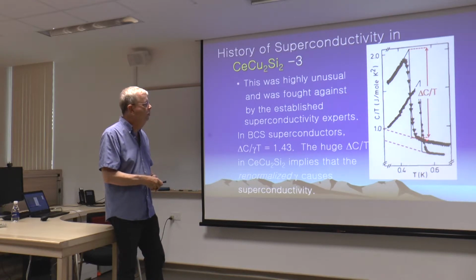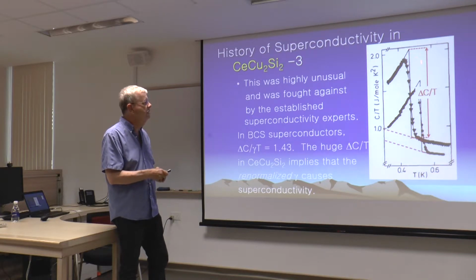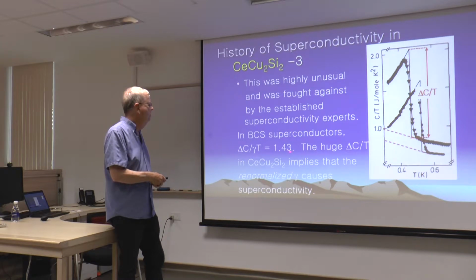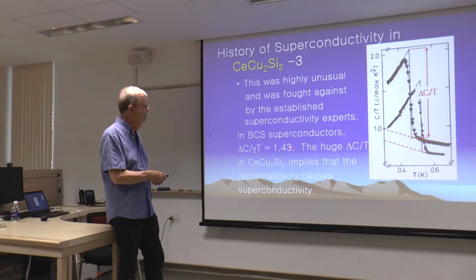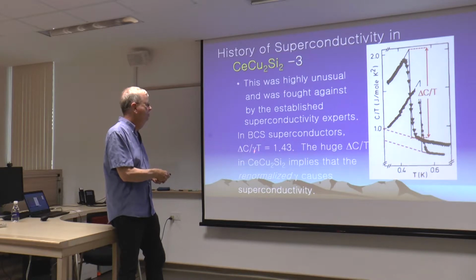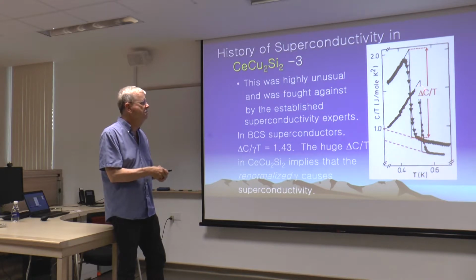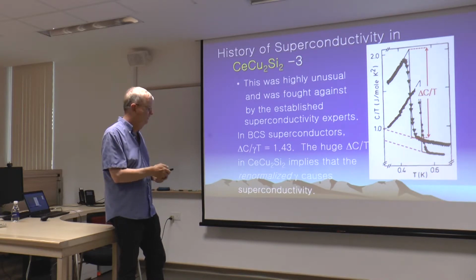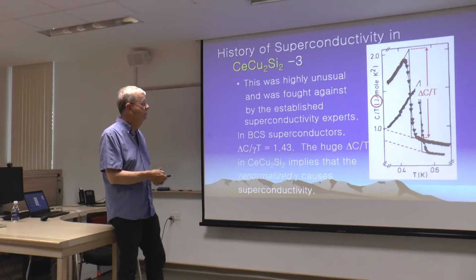So the point here is if you have a large delta C over TC, then you know that this large delta C over TC is due to a large gamma, because remember, delta C over gamma TC, BCS is 1.43, unconventional superconductors, maybe it's 1.1, maybe it's 2, but it's somewhere proportional. So if you have a huge delta C over TC, then you have to have a huge renormalized density of states, highly correlated electrons, causing the superconducting jump, okay? Because this is opening up the gap in the superconductor. This is directly related to the superconductivity, this jump, okay? So, joules, not millijoules.